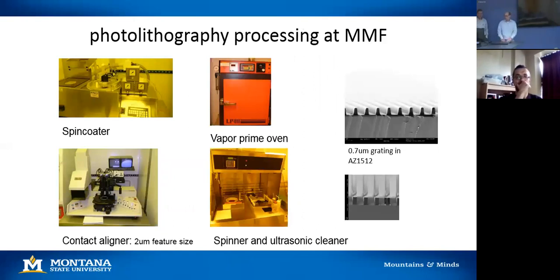Very quickly, tools to go through some of the usage. A vapor prime oven for adhesion promotion. It's very helpful to have your photoresist features stick to your substrate, so it's a pretty common tool. Spin coaters for casting the photoresist. These are all photosensitive polymers in a solvent solution. So we use spin coaters to cast those, although we've now acquired a new tool, which I'll talk about in a bit. Contact aligner, which we use to transfer the pattern from your mask that you'll make with the CAD program into your photosensitive material. Then we have an ultrasonic cleaner for cleaning the masks. These are some basic tools that you can use to get through this process.